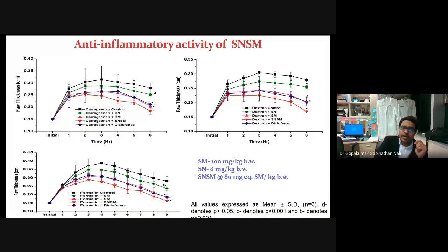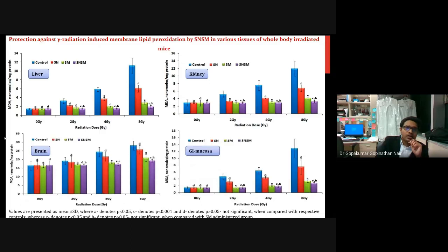So we have studied the anti-inflammatory activity of SNSM, and it was found that even in the acute models and the chronic models, the complex at 80 mg equivalent SM per kilogram body weight of the animal showed very good reduction in the inflammation in the animals. And we have checked the various antioxidant and lipid peroxidation status in the animals, and it was found that the lipid peroxidation was highly reduced after drug treatment in the whole body gamma irradiated animals.